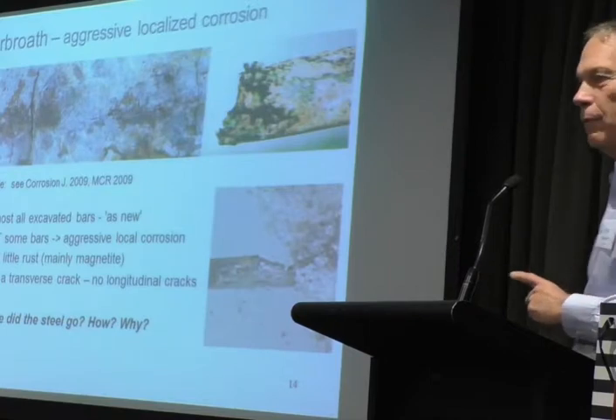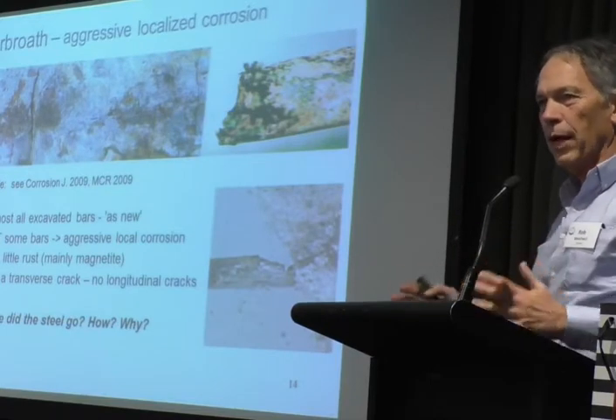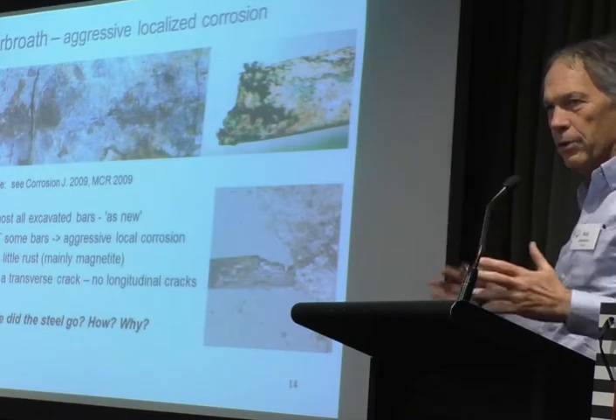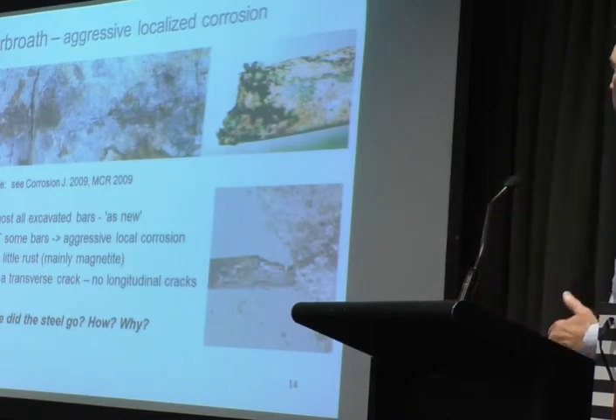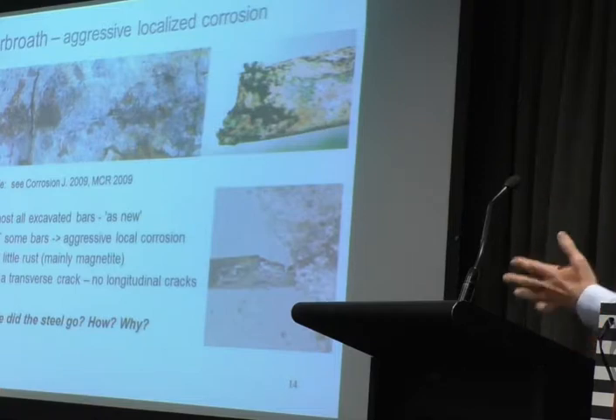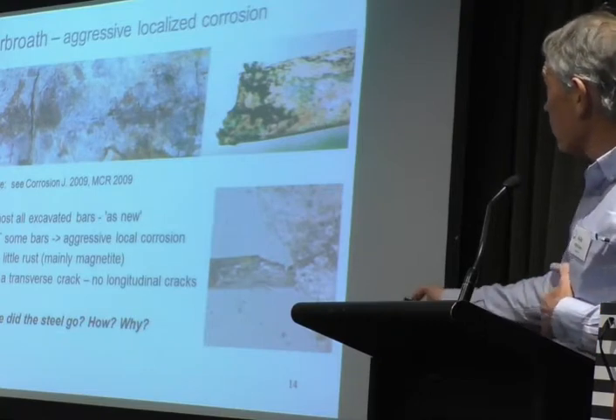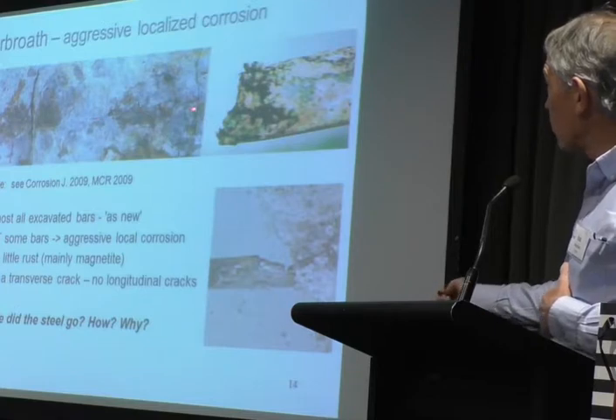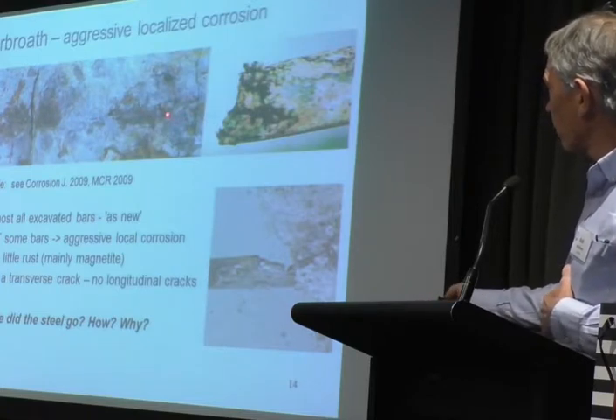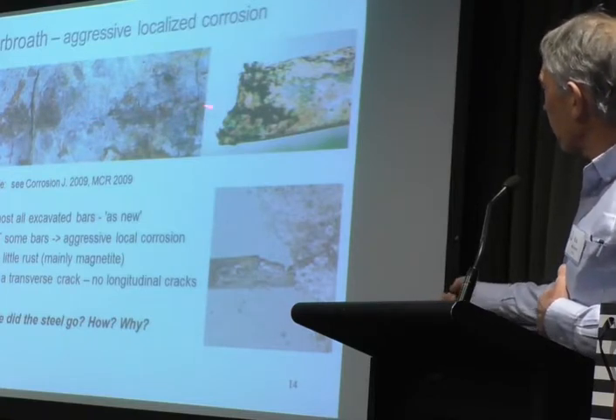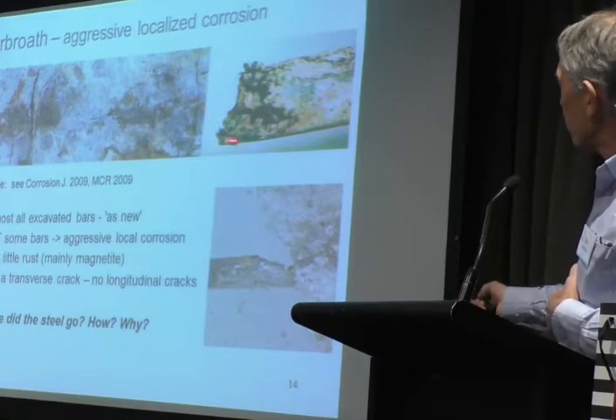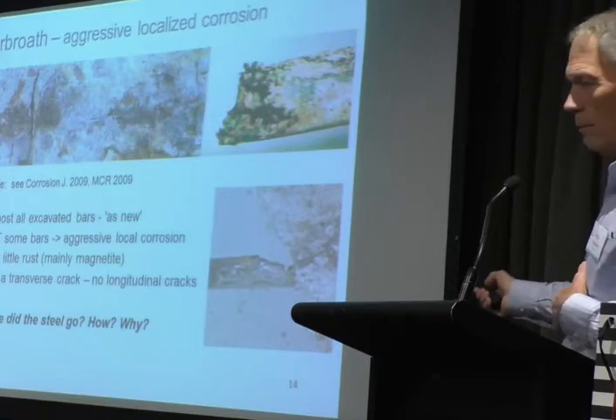At one time, we had some samples, fortunately, that the local council allowed us to take out of those handrails and take back to the lab at the University of Dundee and later on elsewhere. And one day we were breaking up one of the samples that were left over, and I must say I got the shock of my life. It was one of those handrails, and here should have been a bar, and there wasn't. There was nothing left. If we go back further along in this direction, this is what the end of the reinforcement looked like. And I thought, what's going on here?